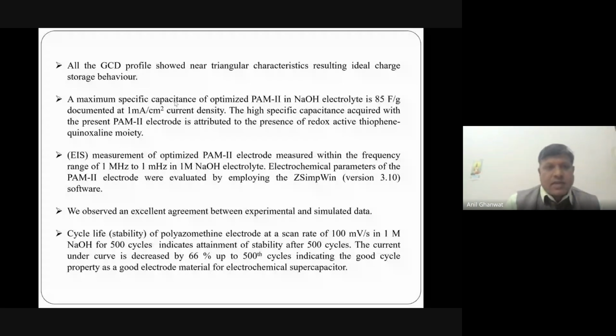Again, we have done the EIS measurements for this PAM2 polymer, and with these EIS measurements we observe excellent agreement with the experimental and the stability data. So the cyclic life or stability of the polyazomethine electrode, we have done at 100 mV/s in 1 molar NaOH for 500 cycles, and that indicates the ultimate stability after the 500 cycles. The current decreased up to 66% at the 500th cycle, indicating good cycle property for the electrode material for supercapacitor applications.